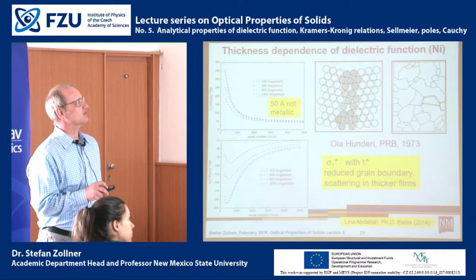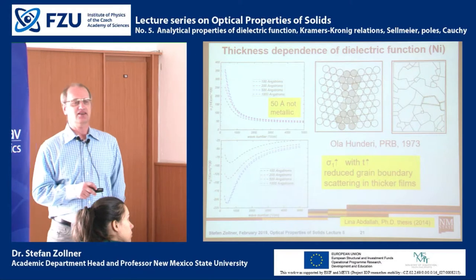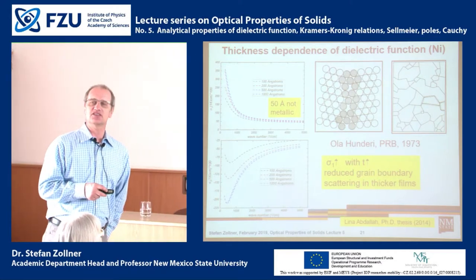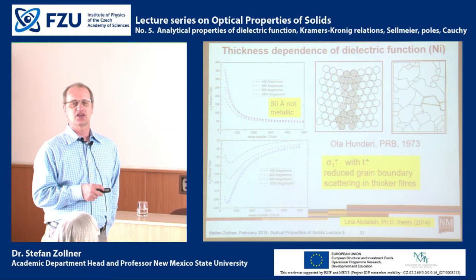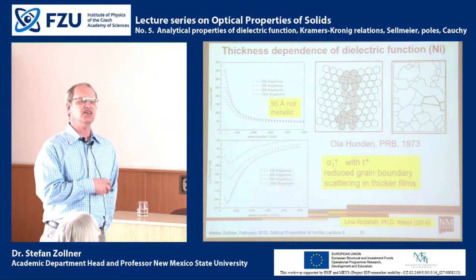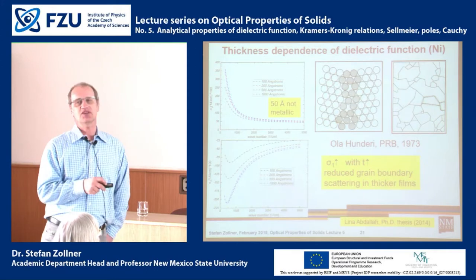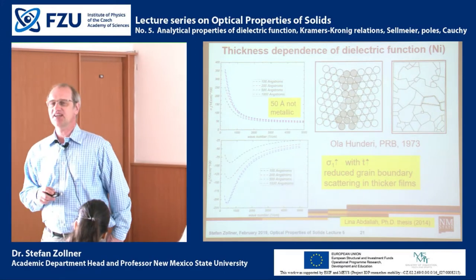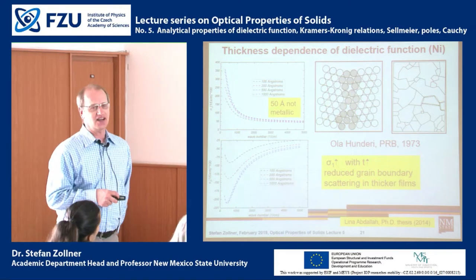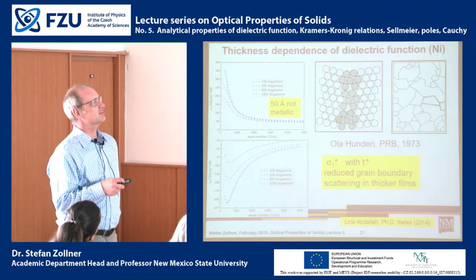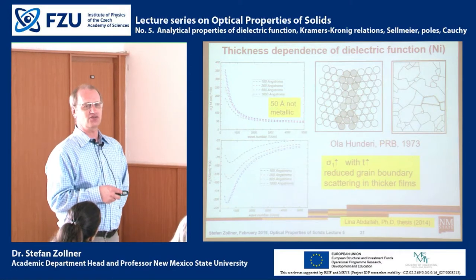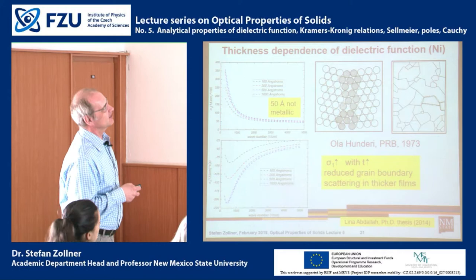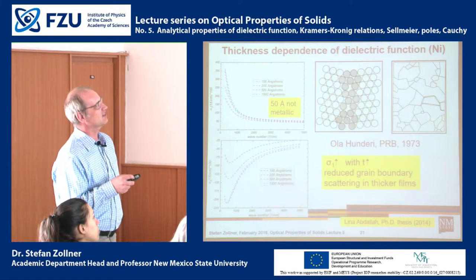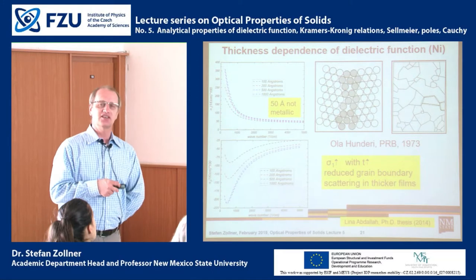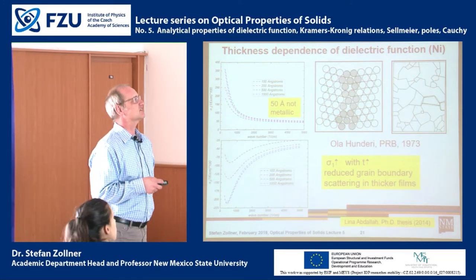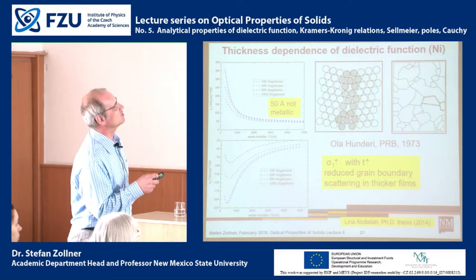When we started with our measurements on thin films, the thin nickel films had significant layers of water on the surface. That's why we need to put the film in UHV and heat it first, and then we take these measurements. But even then, we cannot exclude that there is still a thin layer of nickel oxide. So then we look at the nickel oxide lattice vibrations, the nickel oxide phonons, and then we do simulations. And then we can say, well, if there were 10 angstroms of nickel oxide on top of nickel, then we should see that in some sort of a phonon signature. So doing these measurements is very hard.